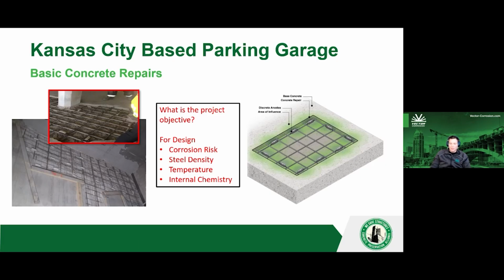In this case, utilizing galvanic anodes in the repair allows us to leave chloride-contaminated, corrosion-driving concrete in place. It can limit repair areas, save time, save money. And I just wanted to show you that these little green halos around the point anodes are the area of influence of each one. We want those little areas of influence to overlap so you have blanket coverage just inside the edge of the parent concrete.